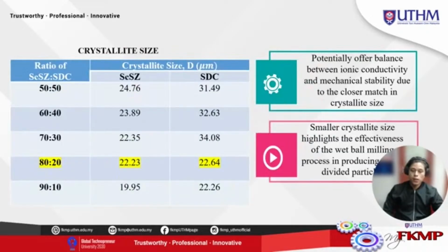Okay, the first one is the crystalline size. The crystalline size shows the result of the 5 ratios, which are 50-50, 60-40, 70-30, 80-20, and 90-10. The closest match in crystalline size is 80-20, very close to the value of ScSZ and SDC, because of the balance between ionic conductivity and mechanical stability. Even though a smaller crystalline size highlights effectiveness, the 80-20 result is very good.